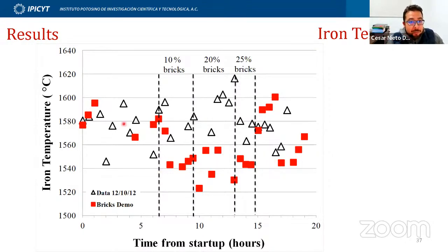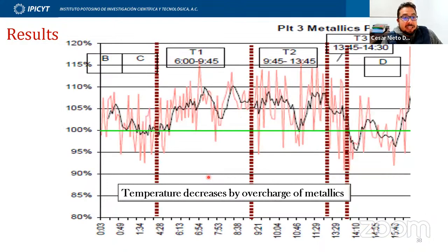And when we started the replacement of the coke with anthracite briquettes, the temperature just went down. We went from 1580 to 1520, which is a lot in a foundry. We were very, very sad, and we saw that the temperature was down, and we were like, what happened with this cupola furnace? Why did it work perfectly in the other one, and in this one, which is a different cupola furnace, it didn't work? But anyway, we collected data, and when we analyzed the data, we got the answer.